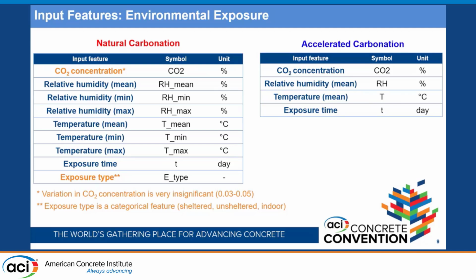For natural carbonation, it is very important to look at the environmental parameters. The ambient CO2 concentration is one of the most important ones. We also try to see the variation of temperature and relative humidity during 1 year of exposure. So we include 3 types of parameters for relative humidity: the mean value, the minimum, and the maximum values. The same for temperature: the annual average temperature, the minimum temperature, and the maximum temperature. Then exposure time and exposure type. In terms of natural carbonation, exposure types could be, as you can see here, sheltered, unsheltered, and indoor exposure. And for accelerated carbonation, we only have the mean values of the CO2 concentration, relative humidity, temperature, and the exposure time, of course.